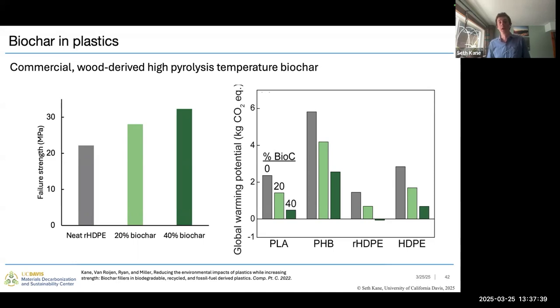And we see a pretty big reduction in the overall global warming potential of that plastics production as a result of introducing that biochar. Because there is so much carbon stored in this biochar, unlike in the biomass ashes, where we were seeing a reduction of about the amount that we were adding, here we're seeing a reduction of about double the amount that we're adding. And that's because of that carbon stored in the biochar. As a result of this, at 40% addition in our recycled HDPE, we can get to negative emissions, and we see greatly reduced emissions at 40% addition in the other plastics as well.